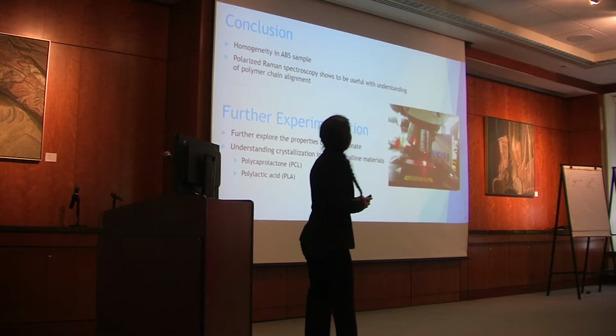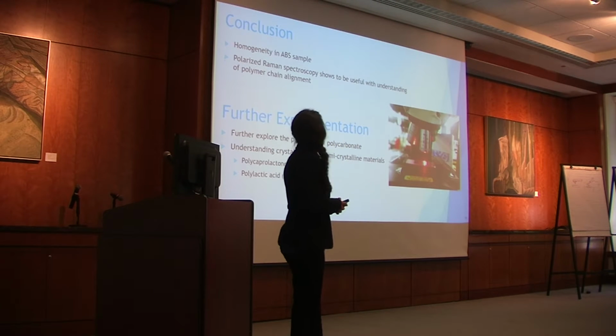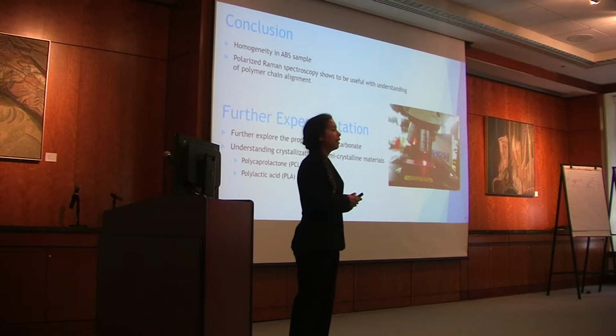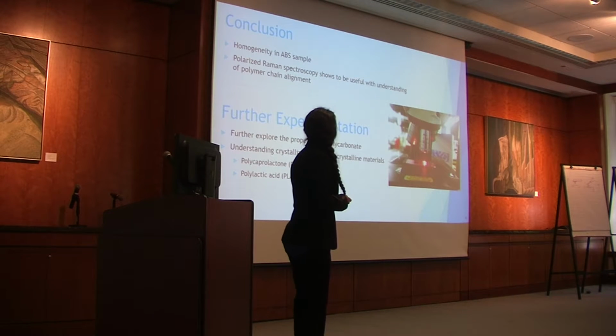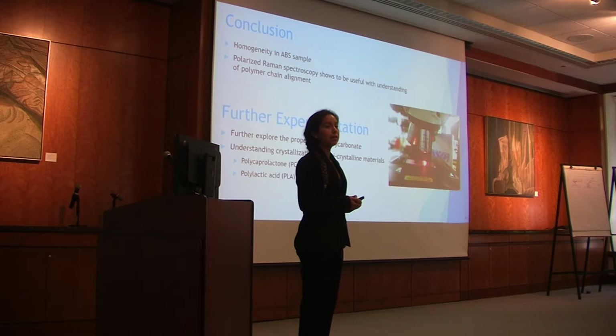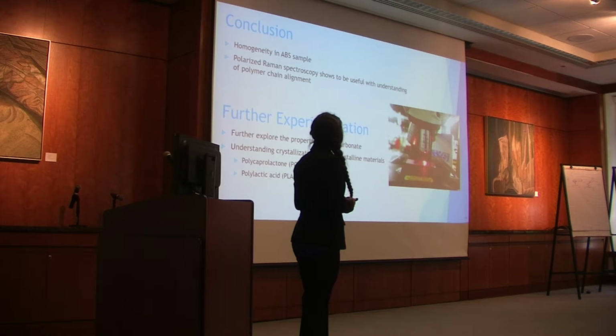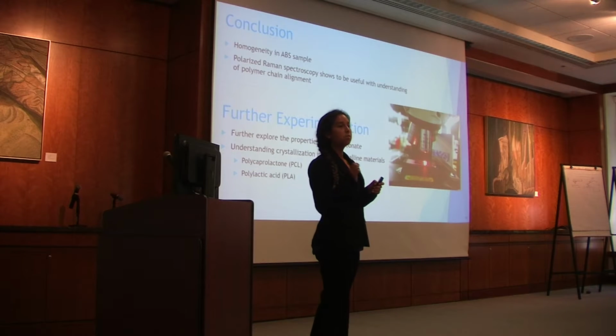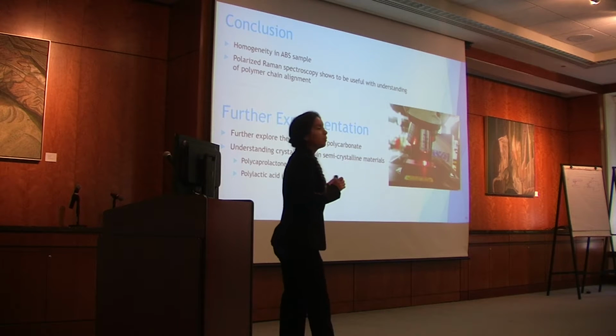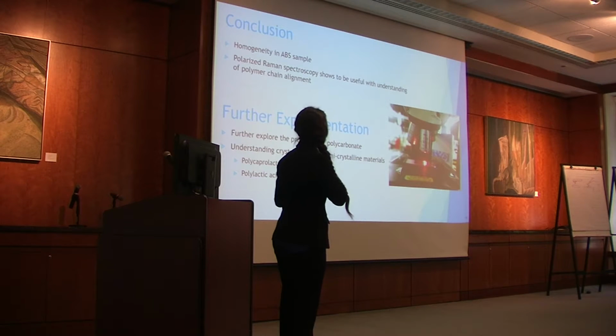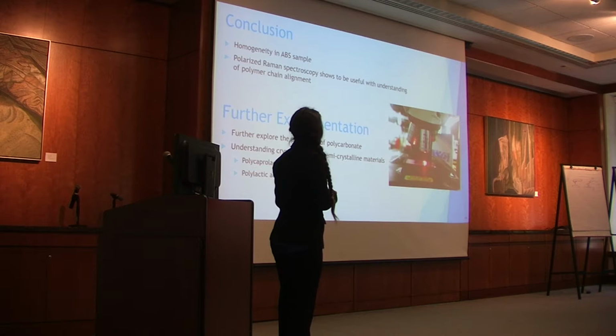With all this in mind, I come to my conclusions. In conclusion, based on multiple scans that were done of the ABS sample, we were able to determine there was homogeneity within the ABS sample. In addition to this, polarized Raman spectroscopy shows to be useful in understanding polymer chain alignment. However, because I did too many projects this summer, of course they can't always be complete. So there is more work.